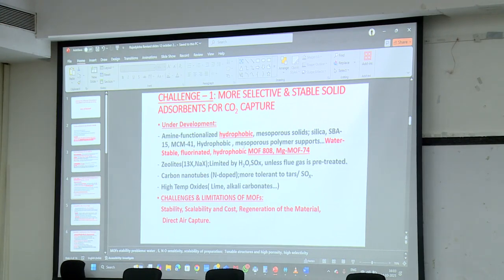Another challenge: we can develop polymers which are hydrophobic and which absorb carbon dioxide. Water stable, fluorinated hydrophobic MOF 808. MOF is metal organic framework. These are the hot materials now. The magnesium one, and this is the zirconium one. They are better than zeolite or other materials. But there are limitations in the MOF process. Their stability is a problem. Scalability: you can make it in small, kilogram quantity, but making it in tonnage quantity is difficult and costly. They are more expensive than zeolite.